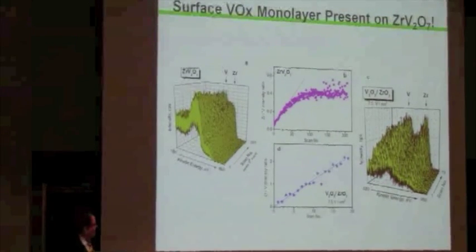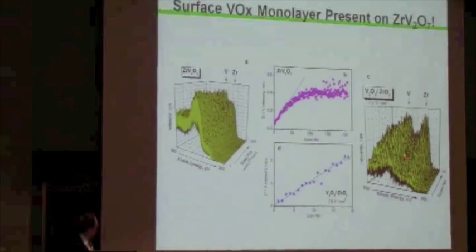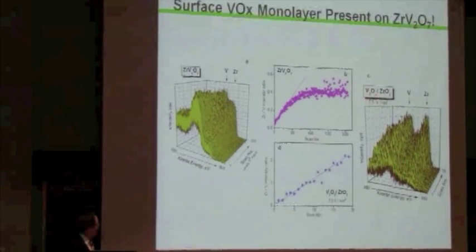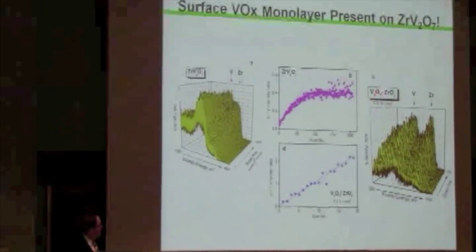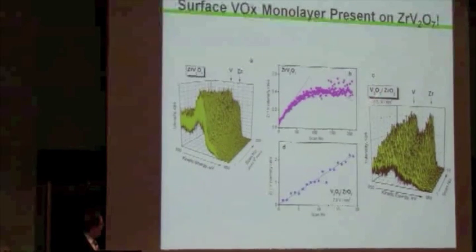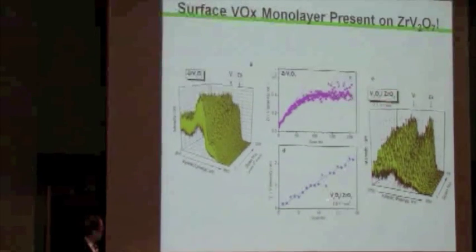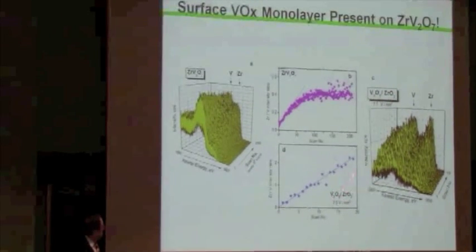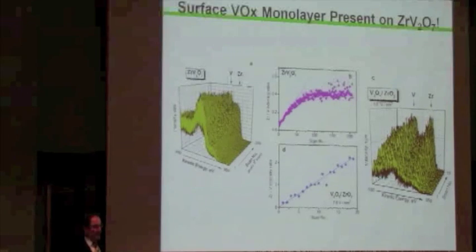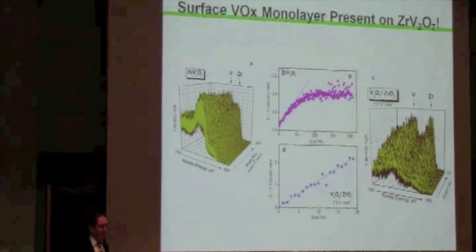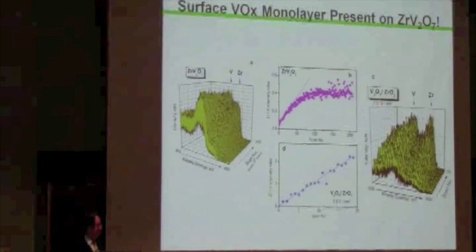we do ion scattering. So I'm actually going to start with the right side of the curve here. This material, in this notation, I've made close to, not quite, a monolayer. A monolayer would be in excess of 8 vanadium per nanometer squared, but I've spread the vanadium over the zirconia. And I have other ways to prove that, which I won't go into right now.